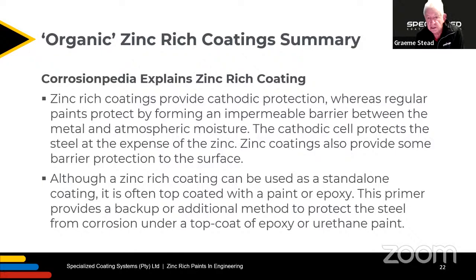Although zinc-rich coating can be used as a standalone coating, it is often top-coated with a paint or epoxy. So there's a whole discussion on duplex coatings for zinc-rich coatings, as opposed to the discussion of duplex coatings for hot-dip galvanized. This primer provides a backup or additional method to protect the steel from corrosion under a top coat of epoxy or urethane paint.